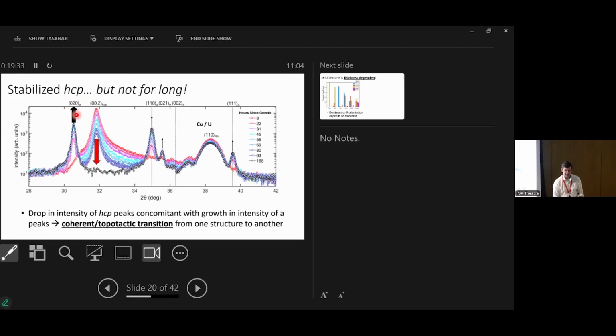It was completely unexpected. I should say, actually, the previous work that Howell did on lanthanum aluminate strontium titanate was completely unexpected as well, completely serendipitous. So again, for young researchers in the audience, sometimes things jump out at you and are surprising. So these are really interesting usually. So this peak decayed over the matter of weeks, and we could follow that and try to understand how this was happening. So yeah, technically this is something called a topotactic phase transition, a structural transition where instead of ripping itself apart and falling into a powder, which often happens, it actually smoothly transformed into a different crystal.